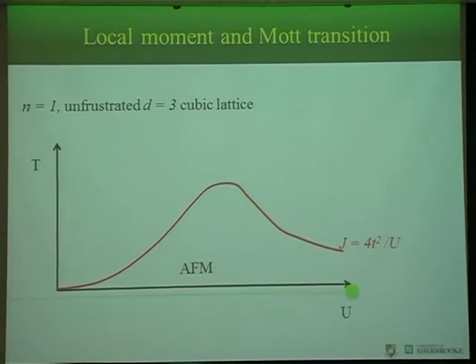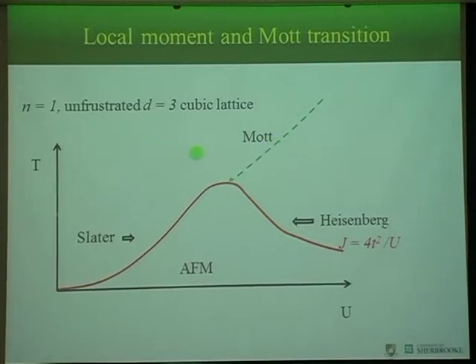So let me rephrase this. This is temperature as a function of interaction strength in a cubic lattice at half filling. Now there is a line I will describe in a moment. Here, this is the so-called Slater mechanism. So it's nesting or just perturbation theory or RPA, give it the name you want, but this is how the transition is described. You go from a metal to an antiferromagnet. On this side, you come from an insulator to an antiferromagnet. So here you have local moments. It's very different. Now this is what's left from the Mott transition. So there's non-trivial physics that goes on here because you need to go from a metal to something that has local moment at finite temperature.